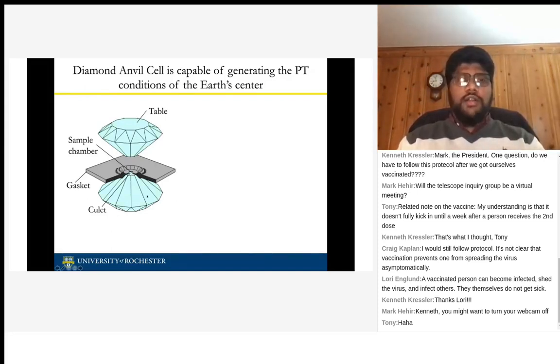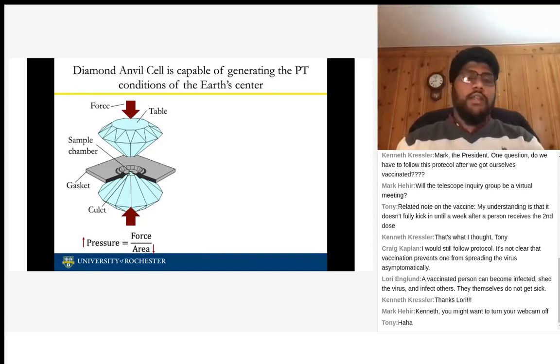You mechanically apply force from the top and bottom diamond, and then we try to squeeze the material in between the two diamonds to higher pressures. In simple terms, pressure is force divided by area. So the smaller the area you go, the higher the pressure you can achieve. Depending on the culet size, the tip of this diamond, you can vary the pressure that you can achieve. In our experiments, we usually go up to 500 gigapascal in the diamond anvil cell. It's more than the pressure at the center of Earth. So the materials that we know at ambient conditions don't really exist in these conditions.